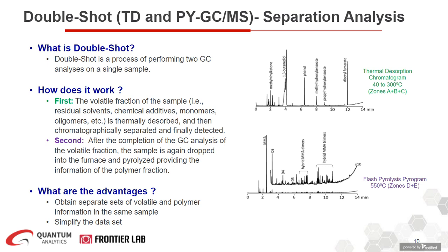So no more solvent extraction. Think of it as a thermal extraction of your additives from your sample. And then second, after the completion of the GC analysis of the volatile fraction, the sample is again dropped into the furnace and pyrolyzed, providing the information of the polymer fraction.